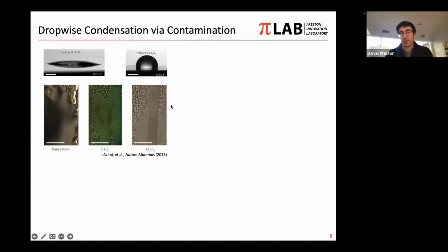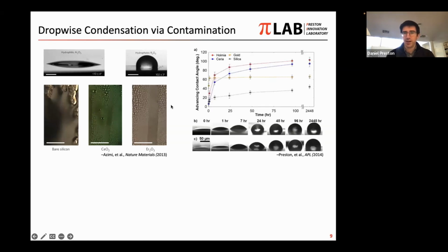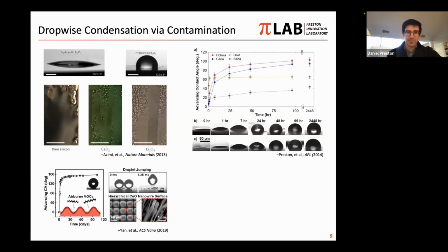In their paper, they said that maybe there's an intrinsic hydrophobicity. In follow-up work that I led, we actually proposed that maybe this is indeed due to some contamination of these high-energy surfaces over time instead. Either way, we get some nice dropwise condensation, and there seems to be a consensus in the following literature that there's this contamination effect that results in this nice dropwise mode of condensation. More recently, people are actually using this to get things like jumping droplet condensation, which can help to push the heat transfer enhancement even further than with just gravitationally driven dropwise condensation.